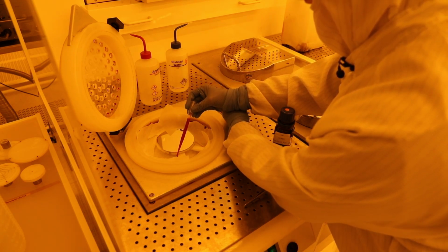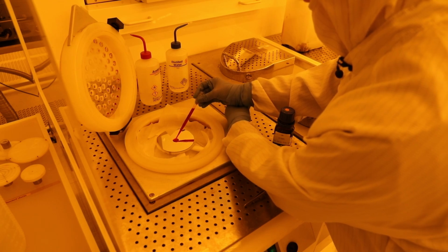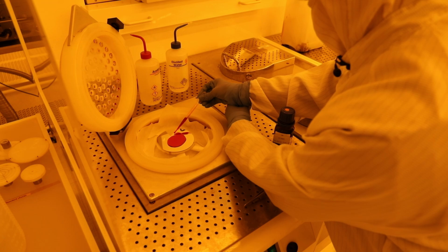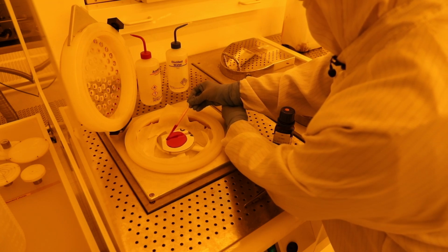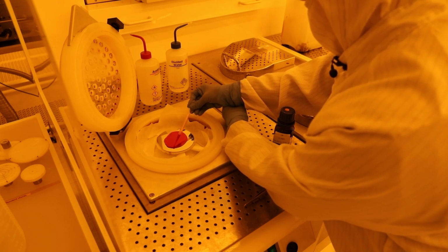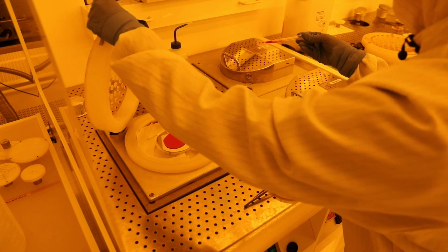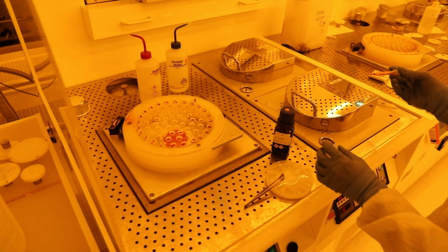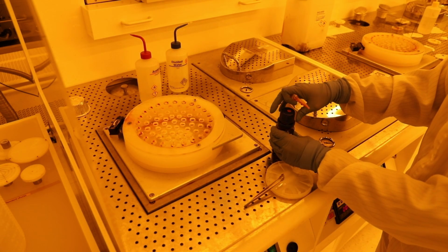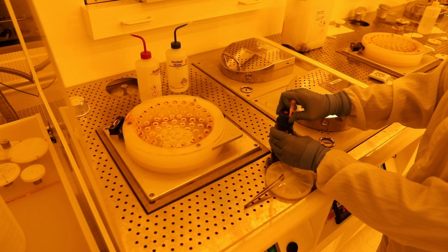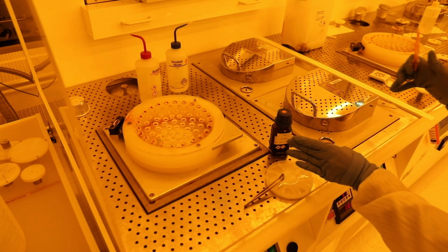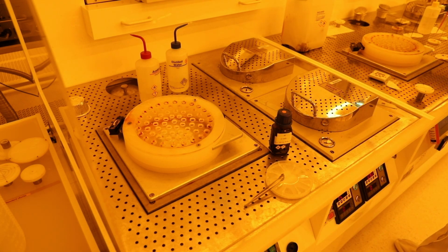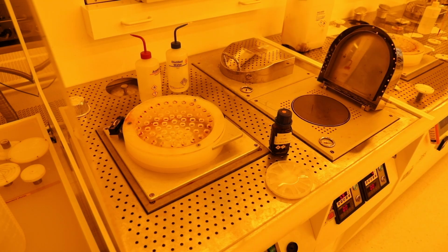We'll deposit the resist on the wafer using the spin coating technique. I have placed the wafer on a spin chuck where it's held in place by vacuum. The next step is to pour some of the resist, which is liquid for the moment, in the center of the wafer. The spinner will then spin the wafer crazy fast to spread the liquid into a uniform thin layer coating the surface. My apologies for the lid of the spinner blocking your view, but it's there for safety, so that in the unlikely event that the vacuum holding the wafer in place breaks halfway through the spinning, the wafer doesn't fly in my face.